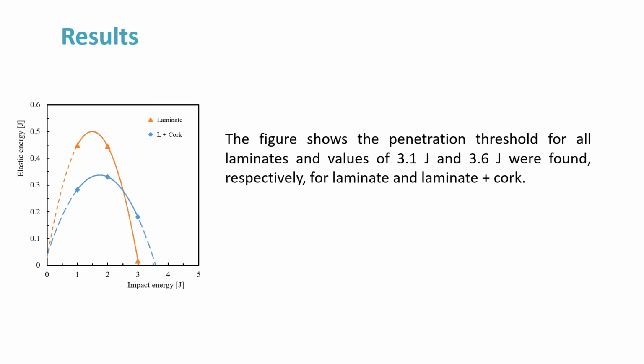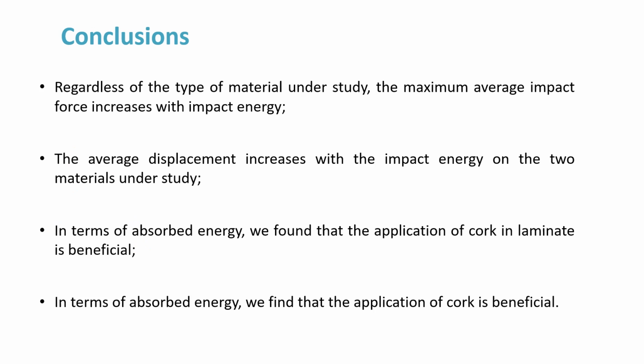The figure shows the penetration threshold for all laminates, and values of 3.1 joules and 3.6 joules were found, respectively, for laminate and laminate plus cork.